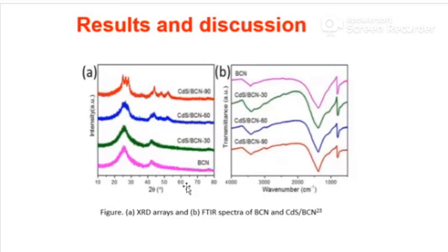The prominent peaks of CdS were evidently observed in the XRD patterns of the composites CdS/BCN 90 and 60 respectively, which reflects the perfect indexing of the hexagonal crystal plane of CdS. This suggests that the crystal structures of CdS and BCN were well established in the composite material.